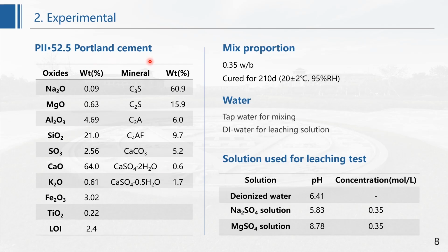Portland cement was used in this investigation. The water-to-binder ratio was 0.35. The sample chosen for the test was cured for 210 days. We used tap water for the mixing of cement paste and deionized water for the preparation of leaching solution. In this study, we used three different solutions for the leaching test. They are deionized water, sodium sulfate solution, and magnesium sulfate solution. The concentrations of the sodium sulfate and the magnesium sulfate solution are the same.